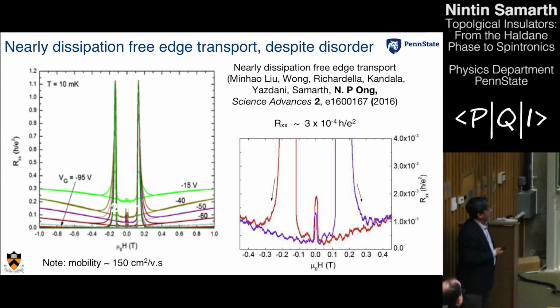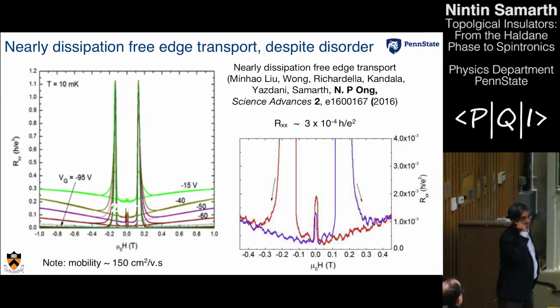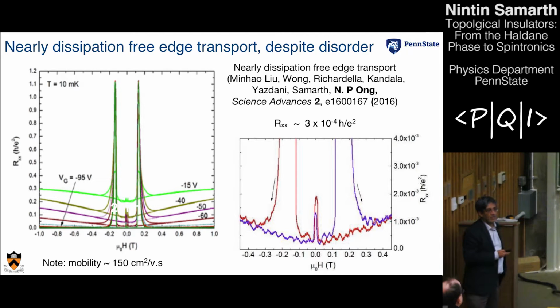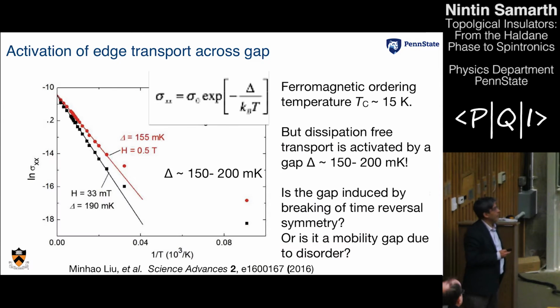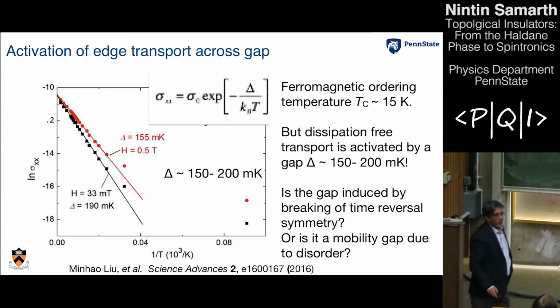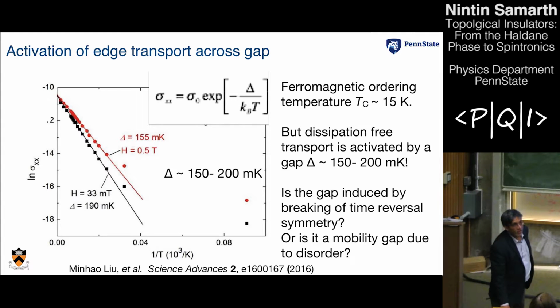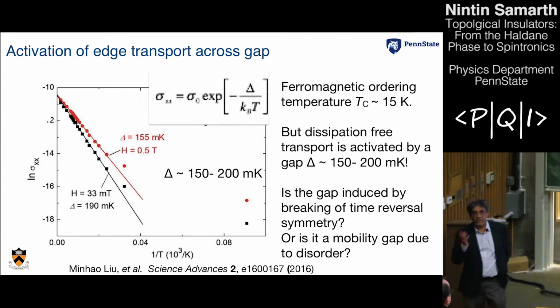And in fact, if you look at the longitudinal resistance, you find that Rxx goes down to fairly low values, a few ohms essentially, in these samples. And again, this is despite the presence of this disorder. Note that the mobility is just something like 150 centimeters squared per volt second. Okay. Now, I told you that there is a gap that is opened up by the breaking of time reversal symmetry. So one question is, what is the size of this gap?